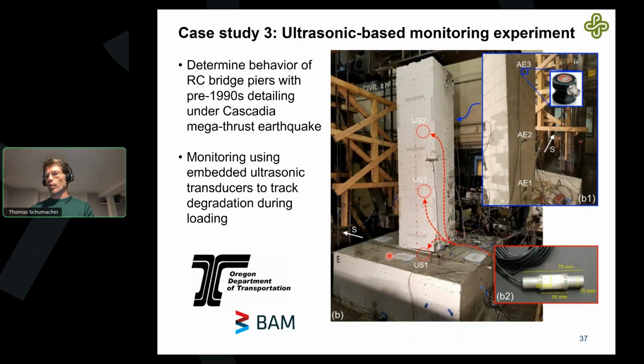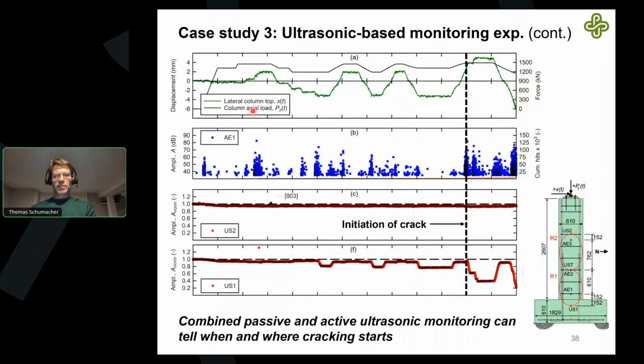Acoustic emission will record cracking and damage that's occurring internally. The ultrasonic transducers here were used so that I basically had an active pulse in the middle, and then the bottom and the top one were recording the response. So here is just the very first phase when we started loading the column. Up here is the displacement and the axial load in the column. With acoustic emission, you start to hear these cracking noises. That's what shows up as you're loading the column, as you vary the displacement.